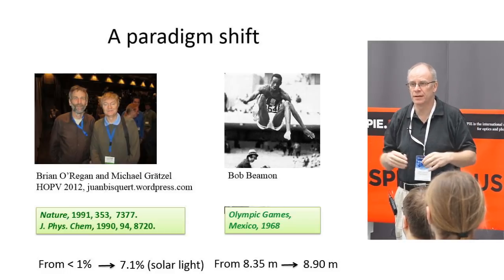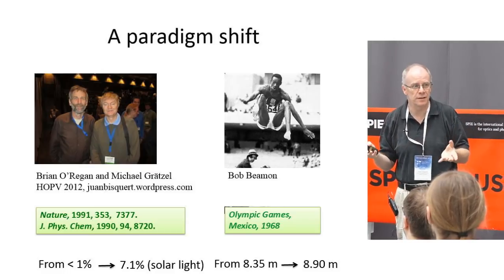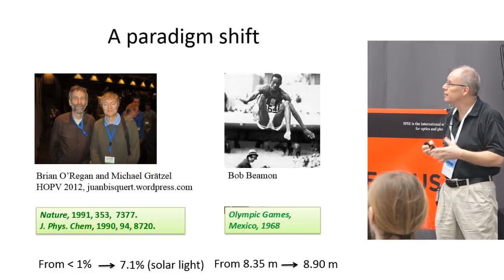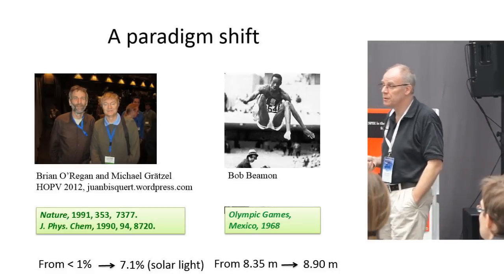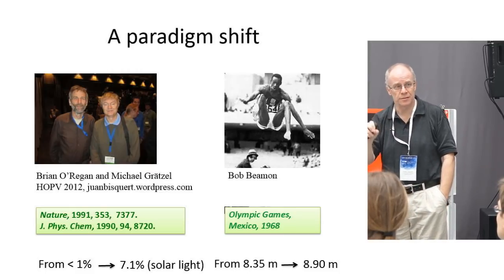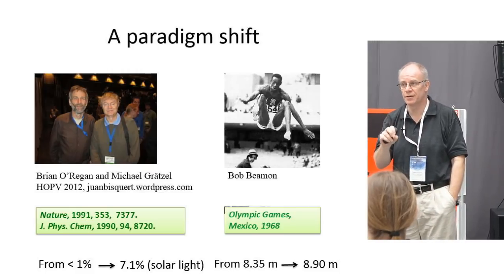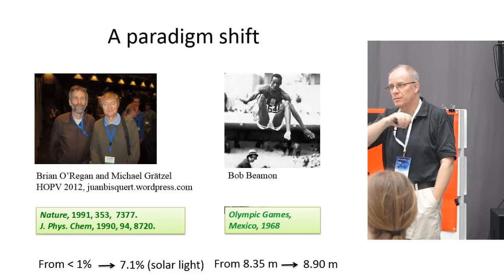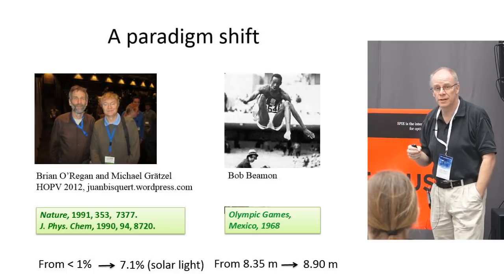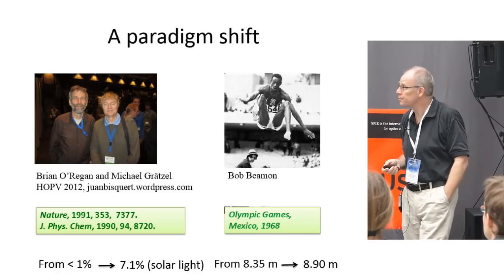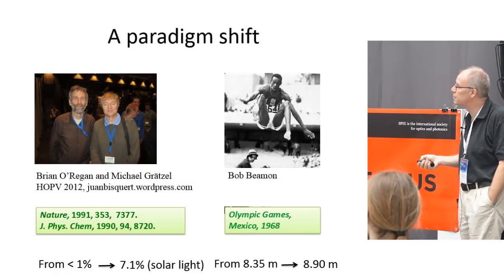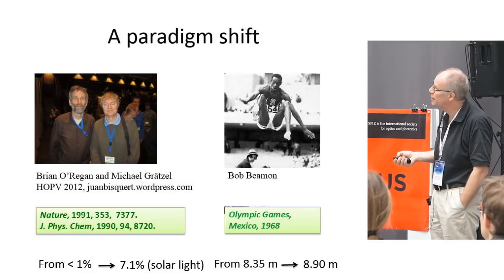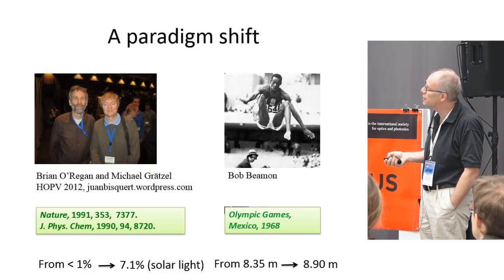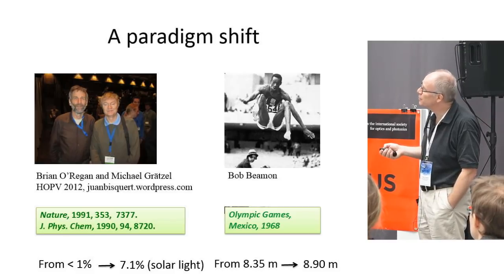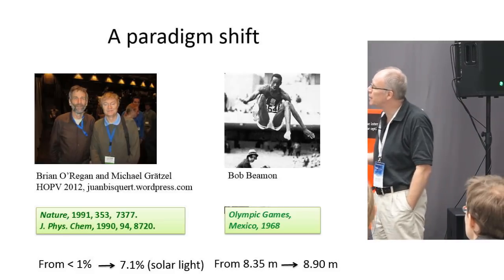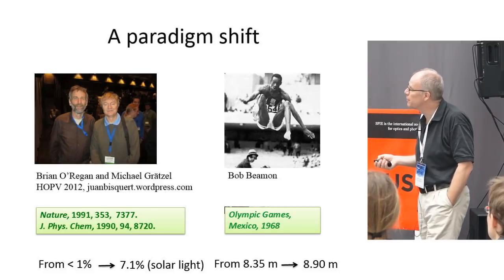It will just recombine. So this was a dead end, basically, at the end of the 1980s, until Grätzel and his group showed another way of getting more dyes on the surface, and that was to use a high surface area electrode. But that was completely counter-intuitive to what people tried to do. So Grätzel and Brian O'Regan published a famous Nature paper in 1991, and here is when I was visiting EPFL for the first time. And I remember Brian here, he made a heroic effort to make these porous electrodes. It took him some years to develop the recipe.